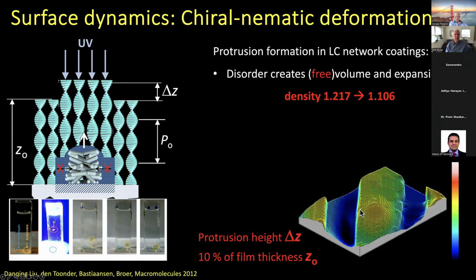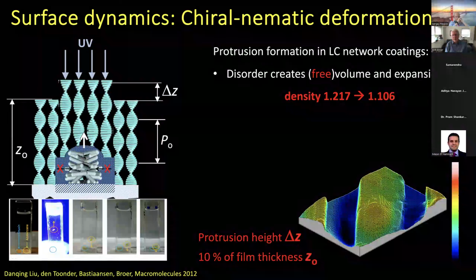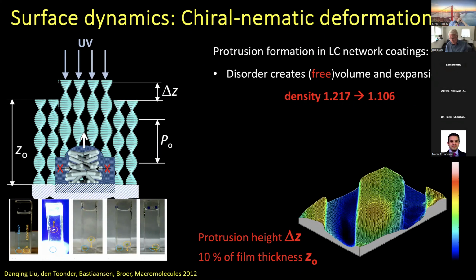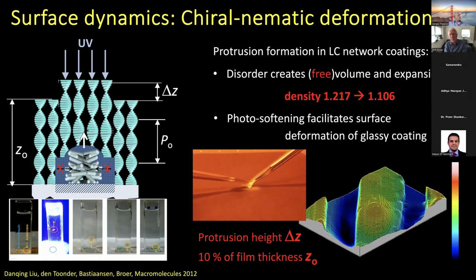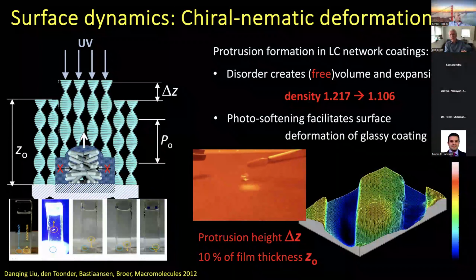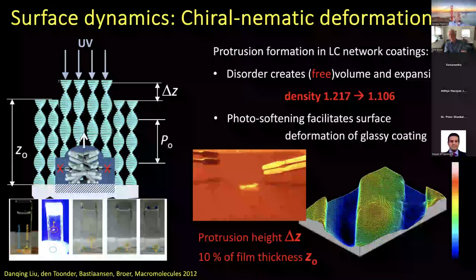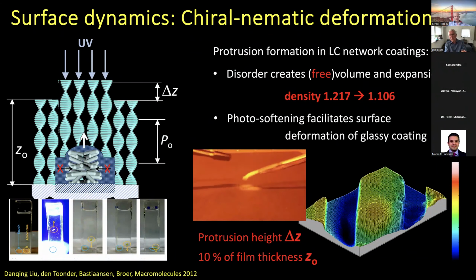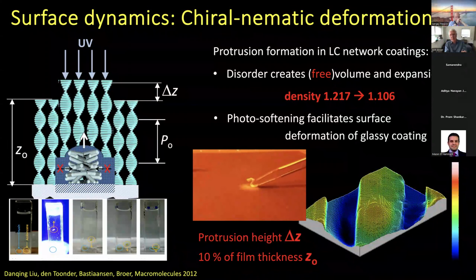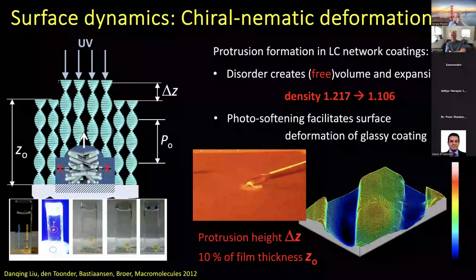But that is not the only thing that surprised us. The materials that we made are glassy, hard materials like Perspex. And it was a little bit difficult to imagine that these films could easily form the surface structure when you are actuating them. For that reason, we also started to look at the mechanical properties, and then we found that during the exposure to light, so-called photo softening took place. So basically, by exposing with light during the continuous action of the azobenzene, the modulus changes. You go through the glass transition of the material, and it becomes flexible. It's shown a little bit in the movie. If the sample is outside the light spot, it is hard and glassy, and in the light spot, it becomes rubbery.